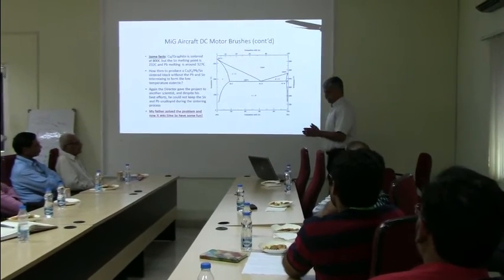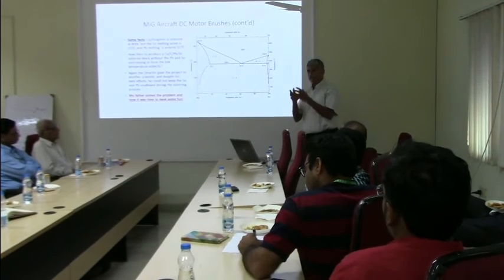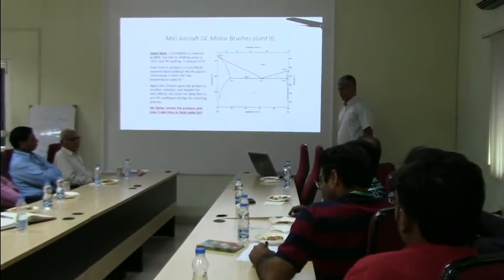So that way you only assure surface diffusion but not bulk diffusion. And so the solution that my father came up with was to use this entire mixture and do hot pressing. You do hot pressing for a few minutes to compact and sinter it so that you get the surface bonding between the particles, but the bulk remains intact. And you can also put all the connecting wires for the brushes in this during the hot pressing operation. So that was an interesting little trick.